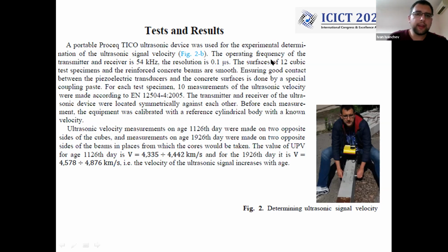1,126th day on the cubes and on the beams at age 1,926th day. So the velocity on the first test day is ranging from 4.34 to 4.44 kilometers per second. And on the second day, it's ranging from 4.58 to 4.88 kilometers per second. So again, we can tell that the ultrasonic signal speed is increasing with the age.